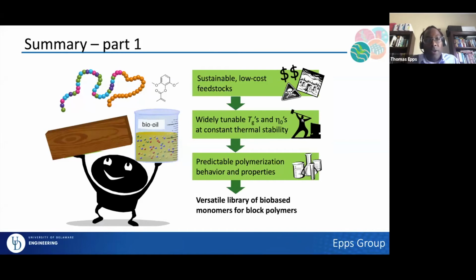So just as a quick summary for part one, what I'm going to mention is that we actually have a material that we believe is a sustainable and low-cost feedstock. I didn't talk too much about the cost of these materials, but we've done some nice techno-economic analysis, which at least on the surface appears to show that they're quite affordable and competitive with some of the petroleum-based counterparts. We have widely tunable Tgs. I didn't talk about zero shear viscosities, but again, we can tune that for various applications. One of the nice things is that given the heterogeneity of the bio-based systems, we still have predictable polymerization behavior, and more importantly, predictable property outcomes, meaning that we can actually then say, if you have a pine tree, it's good for this application. If you have an oak tree, it's potentially good for this application. And we also have that versatility in terms of monomers to make various block copolymers.